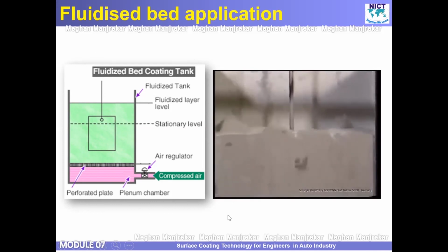Now, the disadvantages are you don't have any control. At the bottom, the amount of powder particles is higher compared to the top. So the DFT variations will be there. Job to job temperature variation. Suppose I put one at 155 degrees, second at 150 degrees, third at 145 degrees. The melting and deposition will vary. So job to job variation in DFT also is expected.